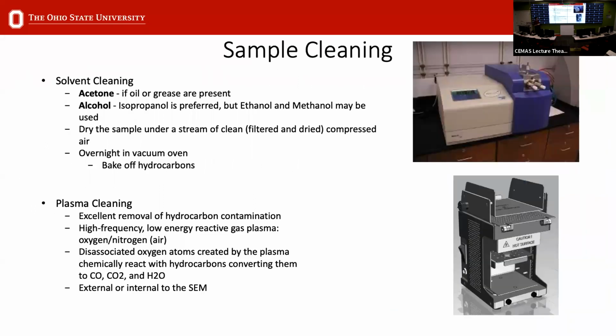So after you're done with your rough polish, your fine polish, and any other additional polish, you want to make sure your sample is clean. Typically, after you finish polishing the material, you want to sonicate it in acetone to remove any oil and grease from your sample if that's present. Acetone leaves a lot of residue on your sample, so you want to use something like isopropanol or ethanol to remove the contamination from the acetone. Once you do that, you can air dry your samples to have a pretty clean surface, at least by eye.